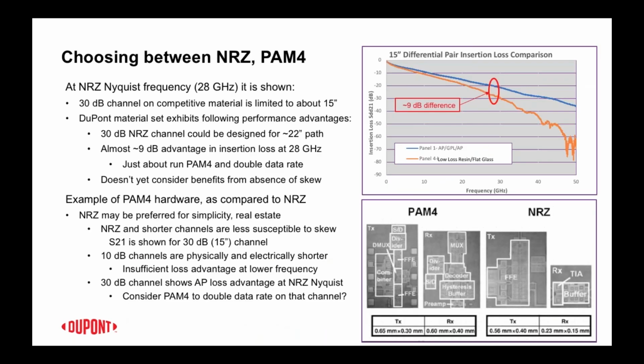So in choosing between NRZ and PAM4, one of the other ways that we're comparing these is that the NRZ signal is limited at 30 dBs. It's limited to about 15 inches. One of the modeling comparisons we did shows that the NRZ channel for the Pyralux material set would enable a path length of up to about 22 inches. The other thing it's starting to show is that there's again, at that Nyquist frequency for NRZ, about a 9 dB advantage, almost enough by itself right there to convert to PAM4. It's got almost enough signal strength at the same frequency. And that's the inference that PAM4, if the material set can be improved upon the incumbent choice, might enable PAM4 to be used at the current operating frequency and achieve twice the data rate throughput.